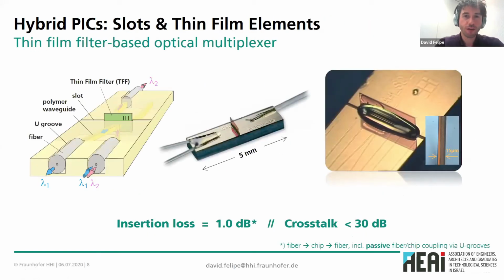An example of a hybrid PIC, a very straightforward example, is a thin film based multiplexer demultiplexer, right? So I mentioned before, you can implement filtering functions on these thin film elements, so that, for example, if you want to transmit two different wavelengths together on a channel, this element will allow you to split them and be able to detect them separately. And this is the level of compactness that one can achieve with this hybrid integration method. This is a very simple element, but the losses are very low. What you can achieve with this is 1 dB losses, and the crosstalk between channels, meaning the crosstalk between wavelengths, can be reduced to lower than 30 dB.